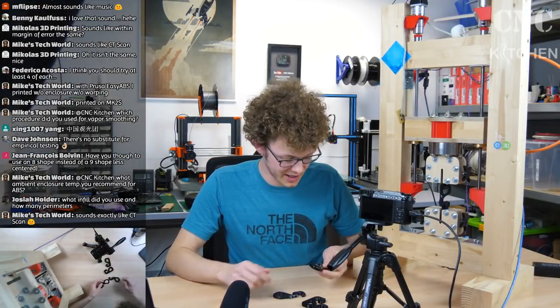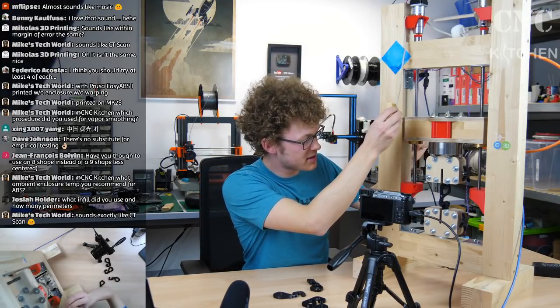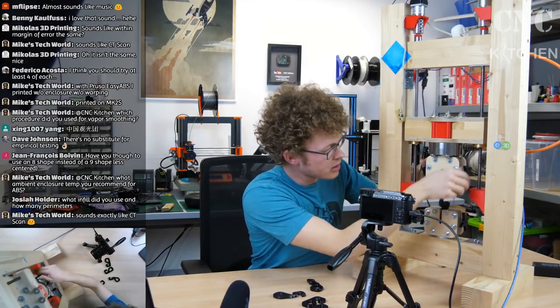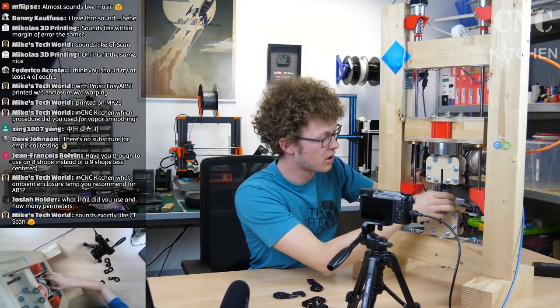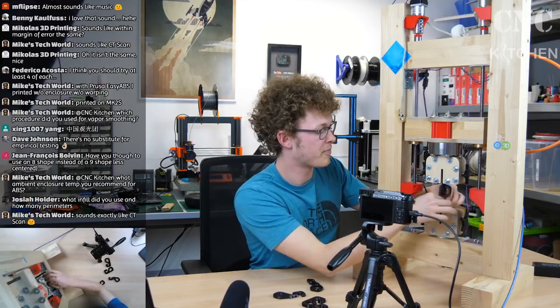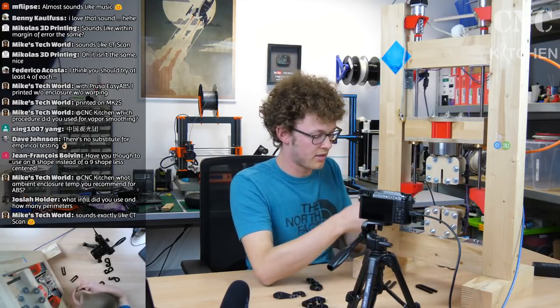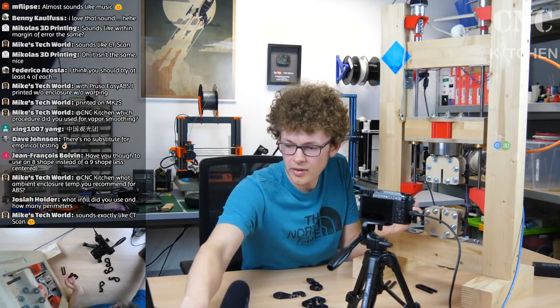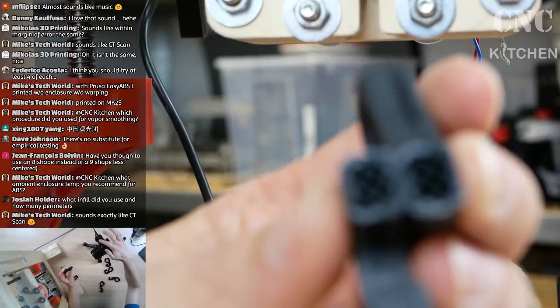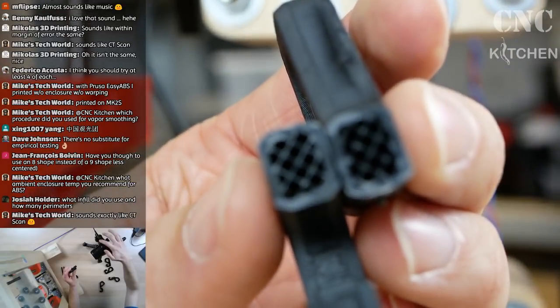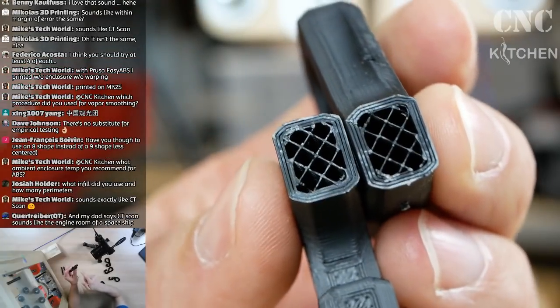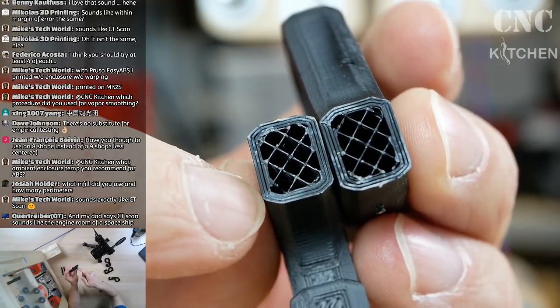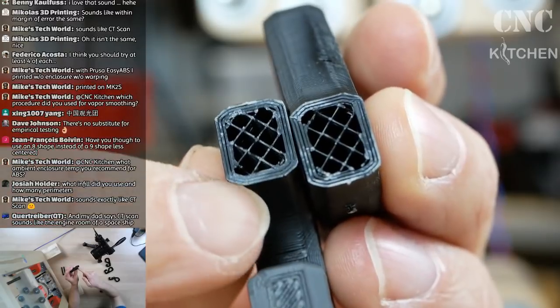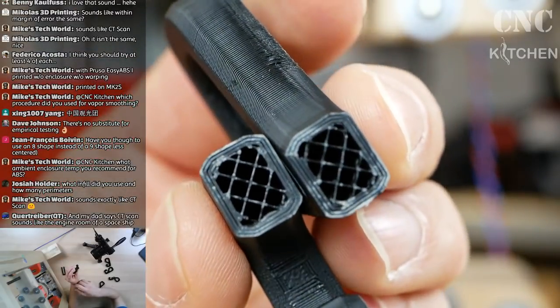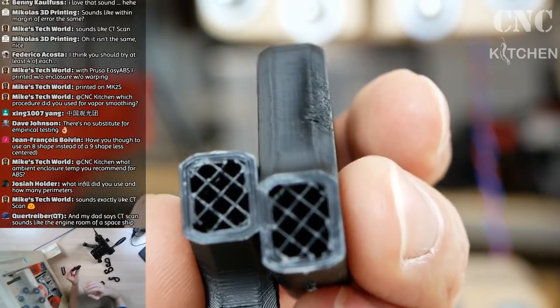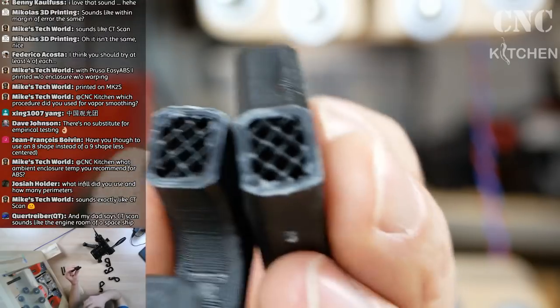Okay, so what have we seen with the ABS specimens? ABS seems to be kind of strong if you print it lying, but the layer adhesion, at least for the print settings that I had been using, is not the best, because the part failed much earlier, and also without any real straining, as you can see right here. Okay, so there are just really some small white parts right here where the material is strained, but you can see that the part more or less sheared off directly in the plane where the part was printed. And this means that the layers did not adhere to each other that well.